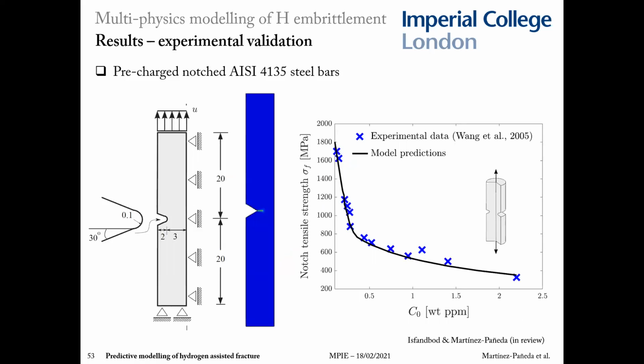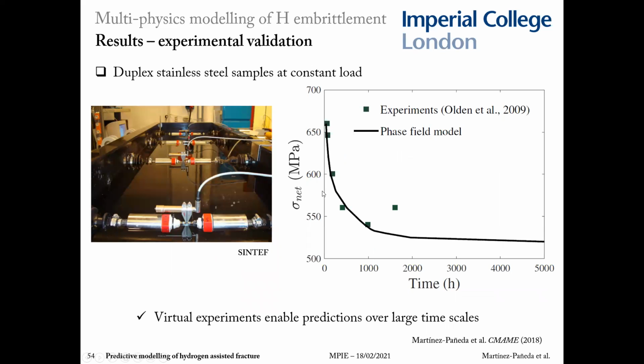So let me move on to show a few representative quantitative comparisons with experimental data. For example, what you see in the slide is a comparison with tensile tests on pre-charged notched steel bars, showing a very good agreement in terms of failure stress versus the pre-charged hydrogen content. Here you see a set of interesting experiments where notched duplex stainless steel samples were held at a constant load in a seawater bath. Each sample is subjected to a different constant load, and all of them fail at a relatively early time from an engineering perspective.